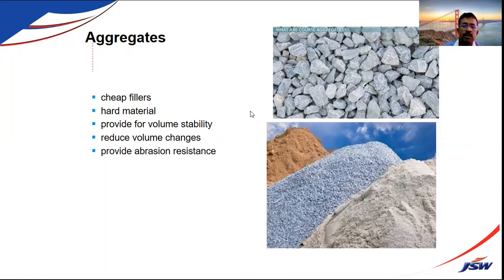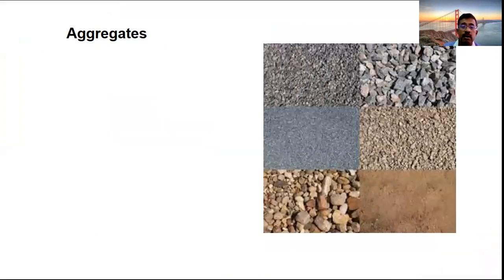So aggregates, very important. The shape of the aggregates, the angularity, the flakiness index of the aggregates, the moisture absorption of the aggregates, very important. Now, for the replacement of river sand, we have got slag sand, which is available, which can be replaced completely with 100%. JSW is manufacturing this slag sand from our Bellary plant and also at Dolvi. So this is gaining acceptance everywhere as a replacement of river sand.